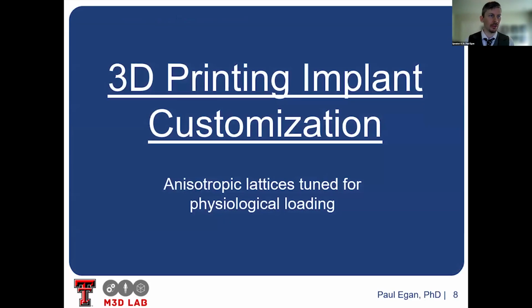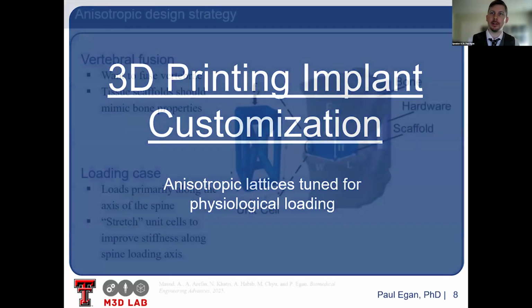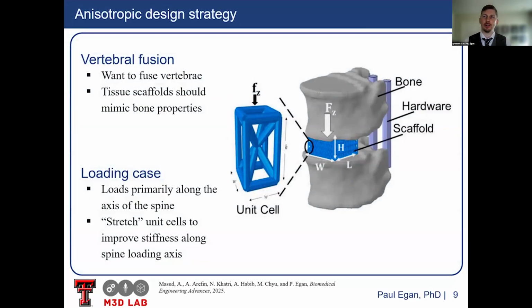And so I'll start with our first case study we're going to look at, which is 3D printing implants that are anisotropic, which is tuned for physiological loading. What we mean specifically by anisotropy is that the mechanical properties are different in one direction compared to the other direction. So if you can imagine in your body how bone is forming in the spine, you have a lot of loading longitudinally, but transverse, you don't have as much loading. And so same with the legs, you get reinforced bone based on the loading conditions it's applied to. And so we want to mimic that with 3D printing.